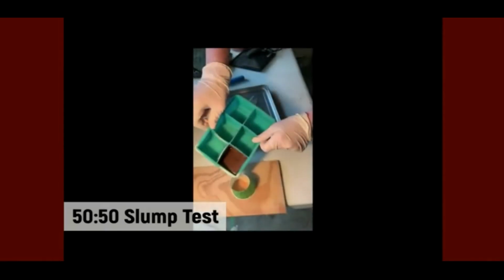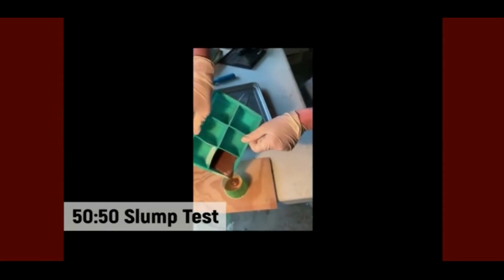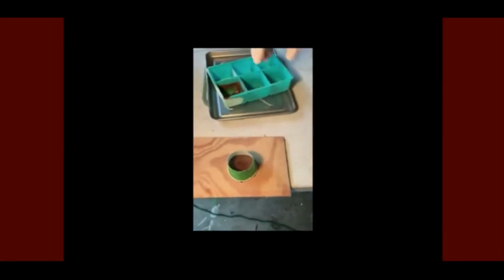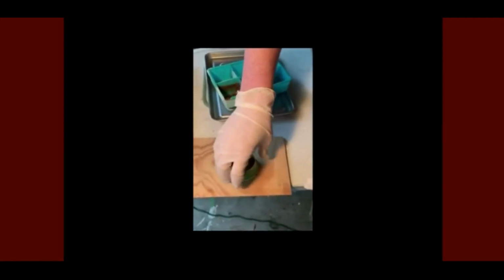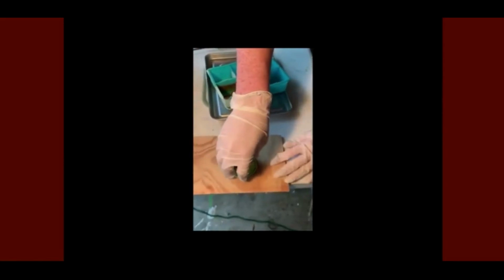So I determined the optimal ratio of aggregate to sulfur for 3D printing sulfur concrete using a slump test, which is a standard construction test to determine workability. Basically, it's poured into a cone, removed, and the slump is measured. So here you can see I modified it using small paper cups.